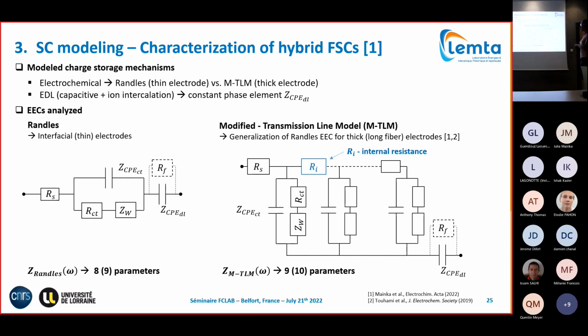And then we have the additional capacitive, so ideal charge storage, meaning at this stage we include the capacitive and ion intercalation charge storage in this element, and this one was represented by a constant phase element that's connected in series to the electrochemical circuit. Note that we tested as well the influence of self-discharge by connecting a leakage resistance in parallel to this CPE, and finally we connected a series resistance, taking into account the resistance of our current collectors and the different interfacial resistances. So two models which have respectively 9 or 10 parameters.